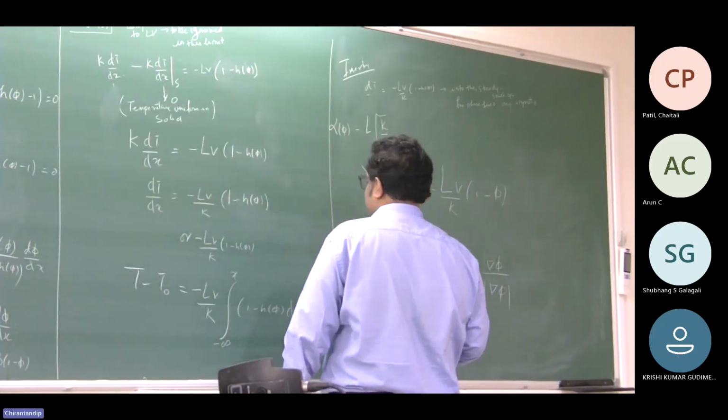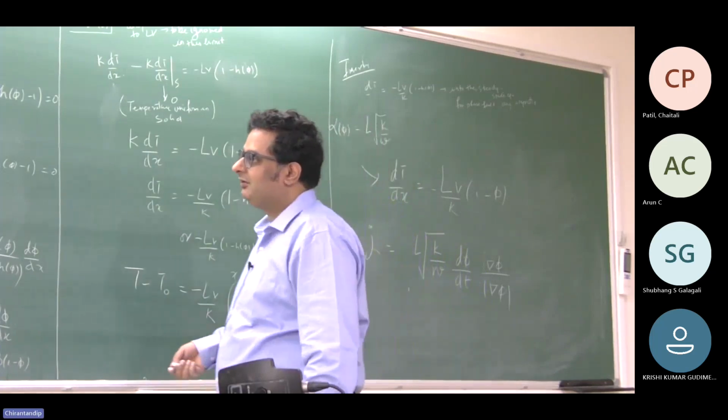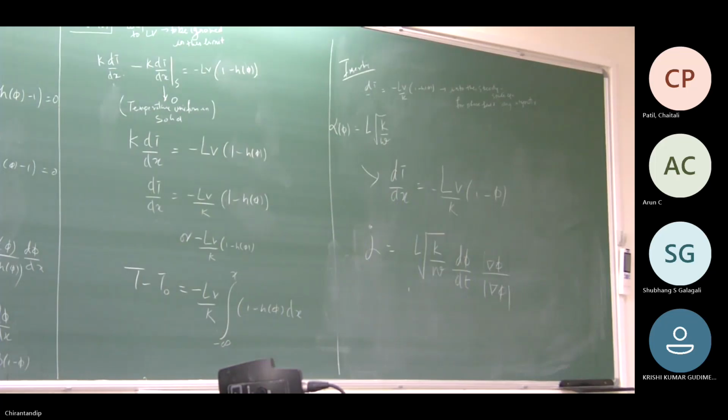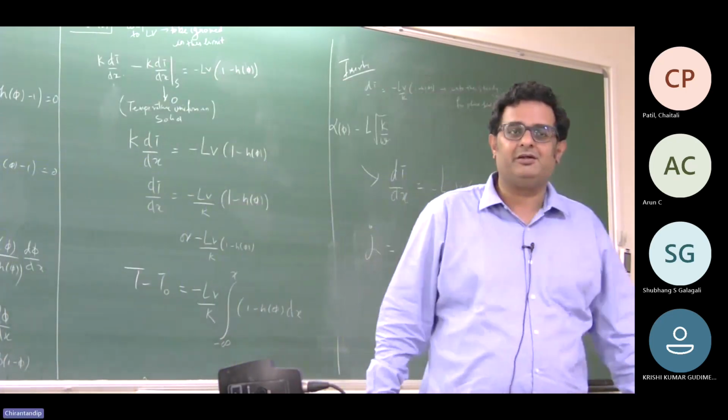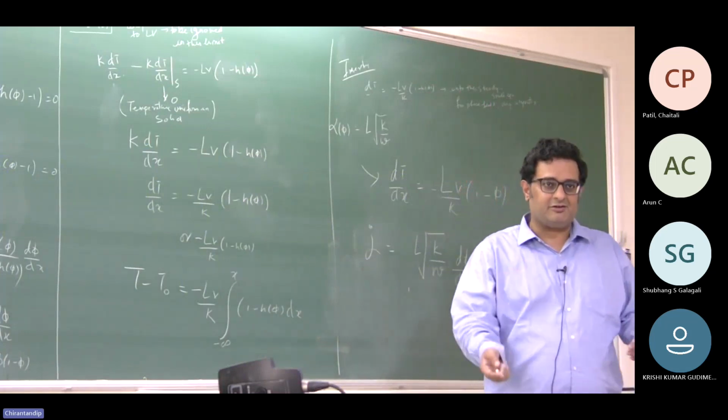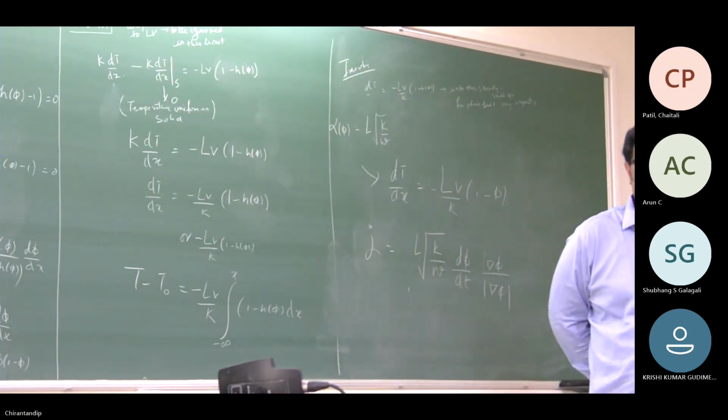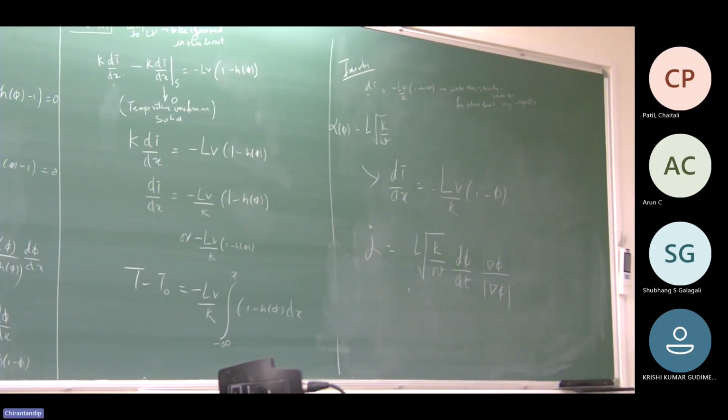Where's K? K is not coming, right? Oh no, the capital K is not coming, and is not required. It's just a function of L. H of phi is phi, the anti-trapping current is a constant. For H of phi not equal to phi, you will get a weighting. Is that okay? Does that make sense?